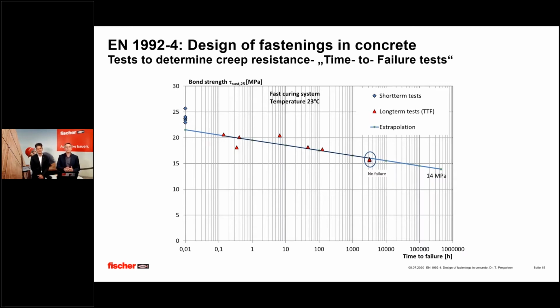The other possibility is our so-called time to failure tests. In time to failure tests, you work with relatively high constant creep loads on the system. They are roughly between 95% and 65% of the short-term reference value. And with doing that, you get relatively short failure times. Short means up to 6 months, a time frame that an anchor manufacturer is willing to wait for his ETA approval.